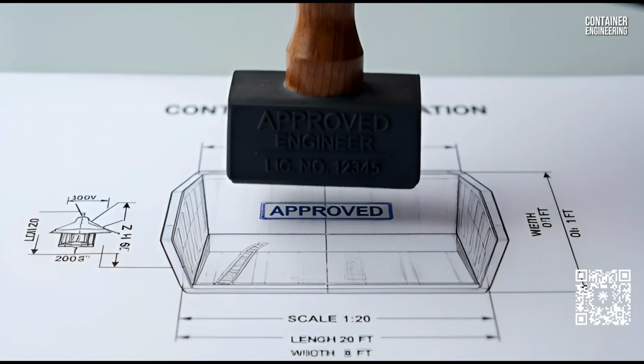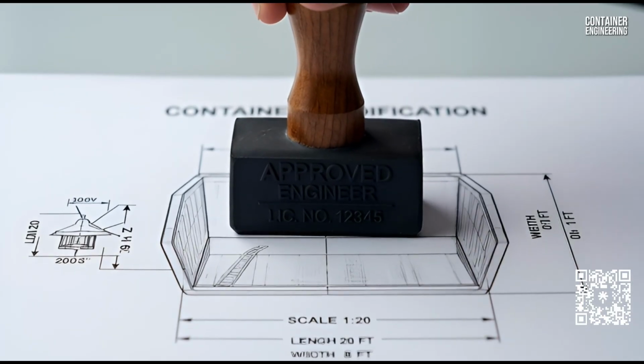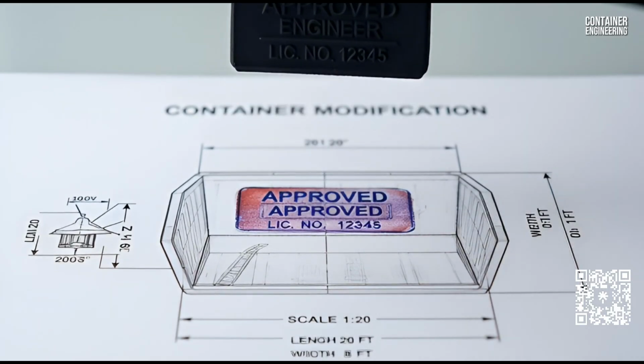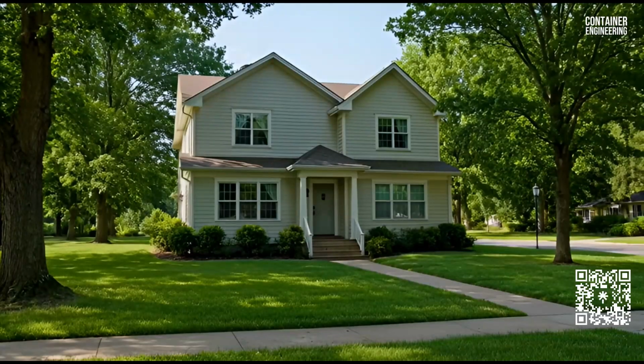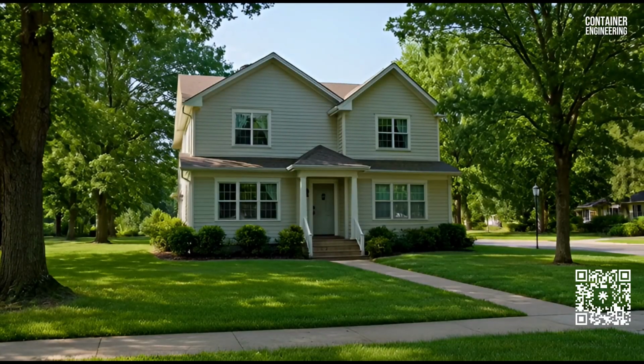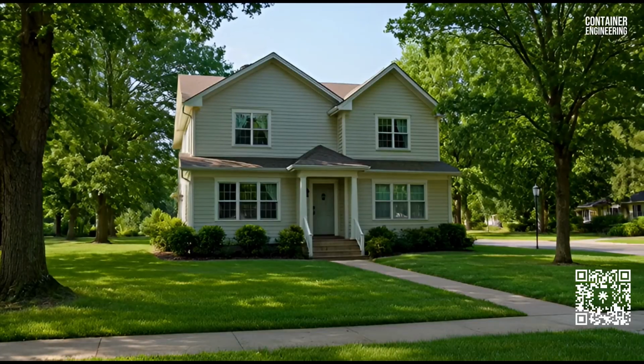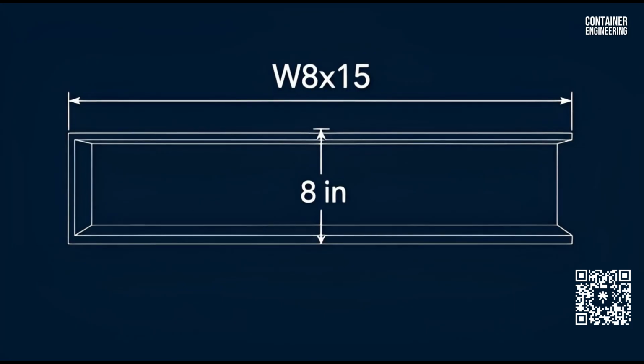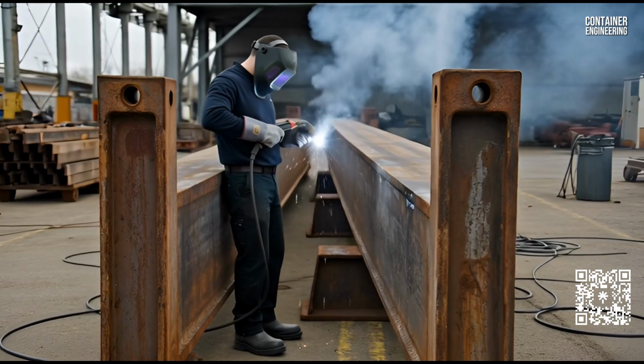Here's the mechanism. Moisture gets trapped between the steel and the insulation. It can't evaporate. The steel surface stays wet for extended periods. Normal Corten protective rust layer breaks down and you get progressive corrosion. A corrugated wall that was originally 1.5 millimeters thick can lose 25% of its thickness in 3 years under high humidity conditions. Let me give you the numbers that matter.